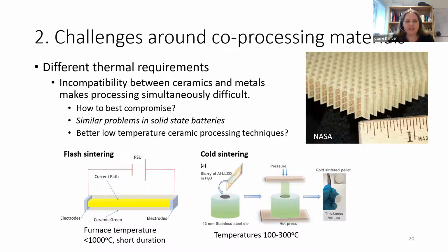So the second area where we've encountered difficulties, and it's not confined to these materials, it's a pretty universal problem, is that if you're trying to co-process materials of different properties, it makes processing very, very difficult. So if you're thinking about processing something that contains a metal component and a ceramic component, if you want to do that at scale, you probably want to process it in a minimal number of steps and preferably do everything at once. So what do you compromise on? Do you compromise on having a dense ceramic that is mechanically robust and will make you a baseline to use that metal for a long time to come? But then you have to take it up to a really high temperature to get the densification, and your metal will melt. So it's very difficult.